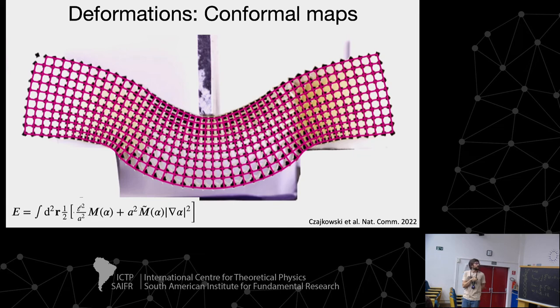Physically, what would this coefficient describe? This coefficient we calibrated, I calibrated, using numerical simulations of a unit cell. To estimate those, what I needed was to compress the unit cell and shear the unit cell, and basically you can get this M tilde. The M you get when you compress your unit cell, and it is typically quadratic in alpha. And this is also, I think, a constant with a correction in alpha. You can get that when you shear your unit cell and measure the stiffness. So it would be like taking this energy function as a toy example to do calculations with. We would not have any problem considering that as a toy problem, for instance. Here what we did was estimate this from the microscopics using numerics. But you could also do a Ginzburg-Landau argument where you just take the leading order. And it seems like, if I understand correctly, that's what you're proposing.